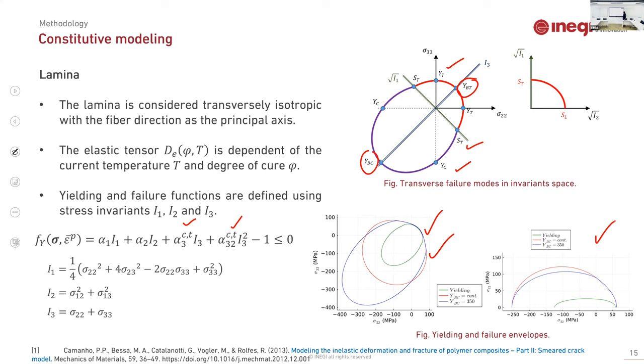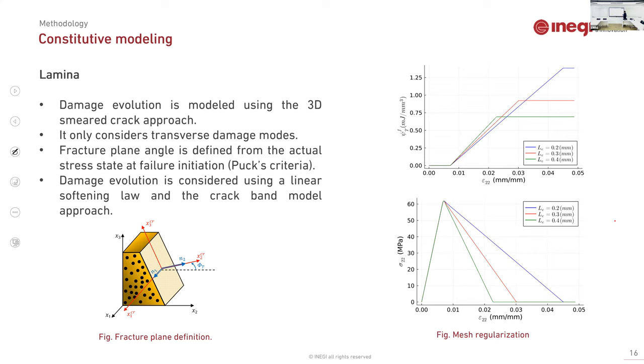Okay. This is only for yielding and failure initiation. But the model continues to be more complicated. After the failure is reached, we need to consider also the damage evolution. The damage evolution in the lamina model is more complex than in the resin because the material is not isotropic. For this, I have implemented the smeared crack model. The smeared crack model is based on the Puck criteria. Depending on the stress, we need to define a fracture plane, okay? And there are some damage models that will say how the material will break until the failure.